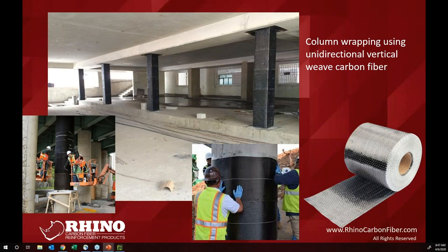Is the epoxy coming through the carbon fiber? Is that what's happening? When you do this kind of an application, you're dealing with a primer coat, and a base coat of epoxy. I'm going to say it in mils because it's how I know it. You have a primer coat that's 10 to 15 mils thick. You'll have an epoxy base coat that's 15 mils thick, 45 to 60 mils of carbon fiber, and then 15 to 20 mils of top coat. That's how the process works to create an encapsulated composite. And that's all there is to it, really. And then we top coat.